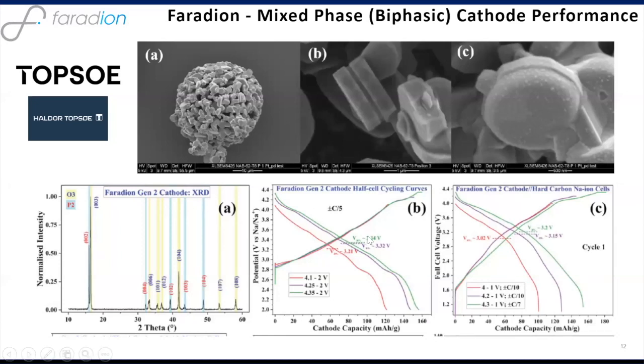And to illustrate that, these voltage profiles here, the center one in B shows the voltage profile in a sodium metal half cell. And you can probably see there, we're delivering a reversible specific capacity of approaching 160 milliampere hours per gram. For those of you who are not sure about what that means, that's a similar figure in terms of milliampere hours per gram specific capacity to what you would get from a lithium iron phosphate cathode material in lithium ion.